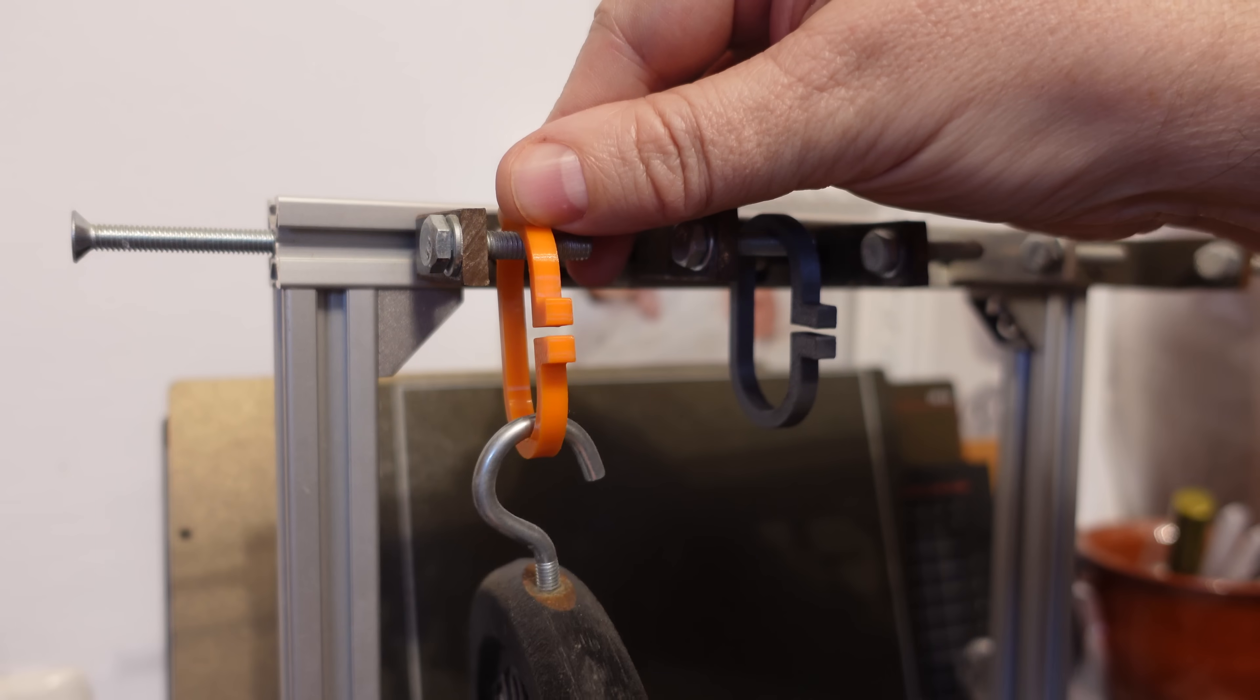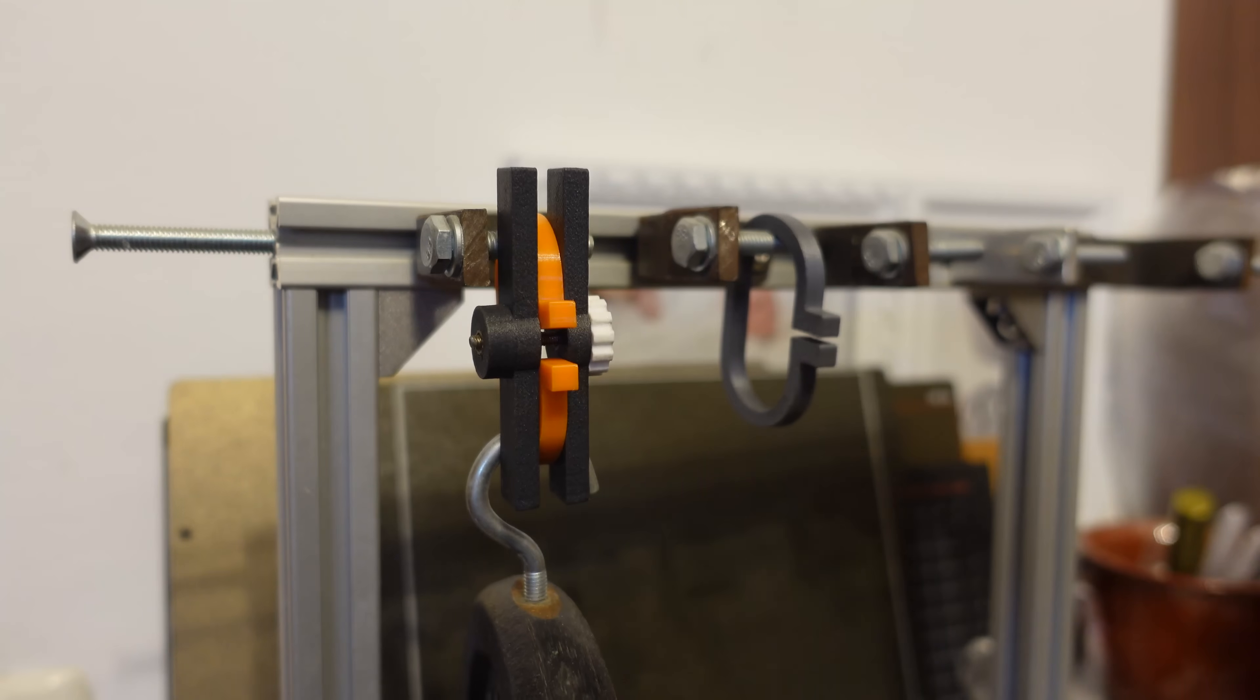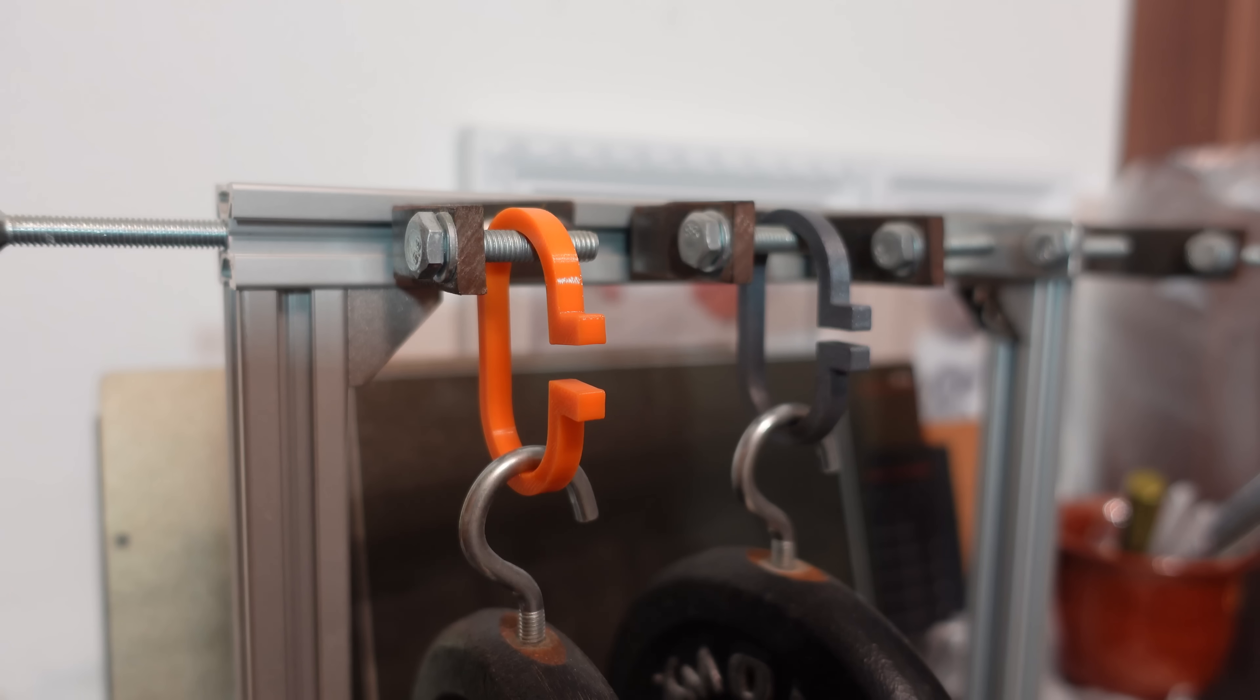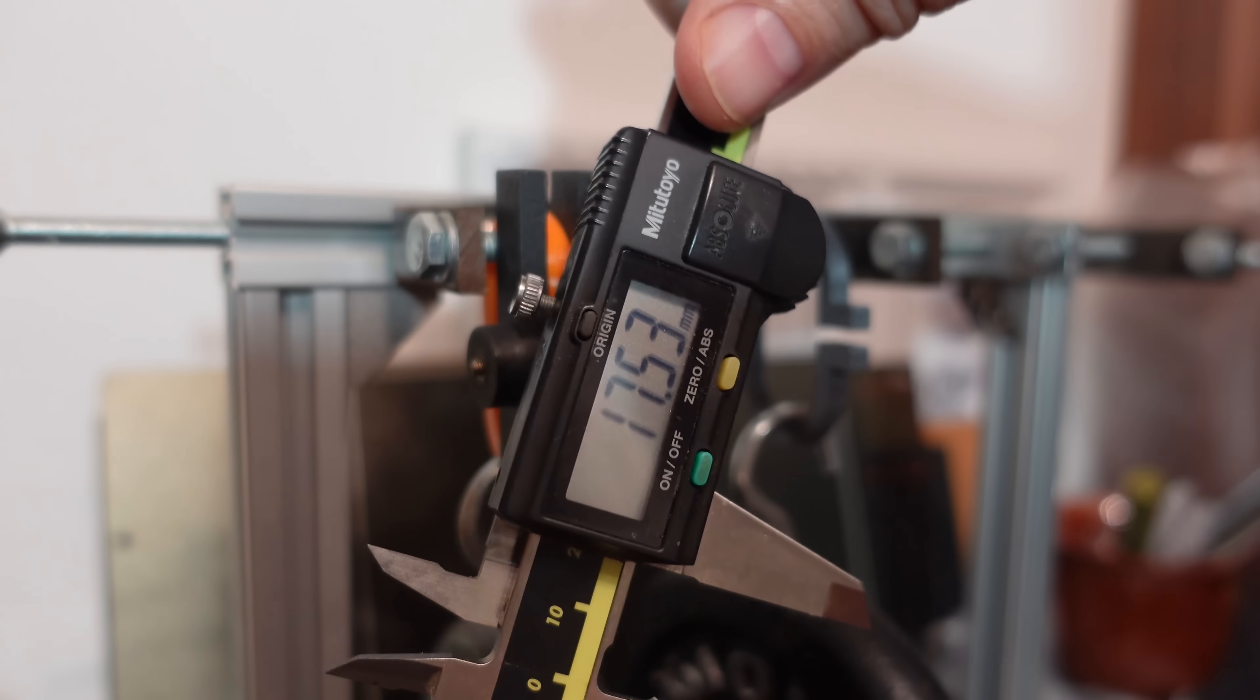Creep test, the deformation under constant load of 1.25 kilograms. Locking the position for more accurate measuring. 16.66 initial deformation. Day 5, the last measuring. Again locking the position. 17.53.